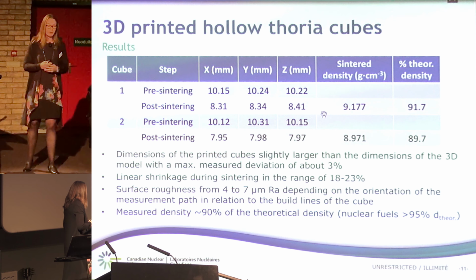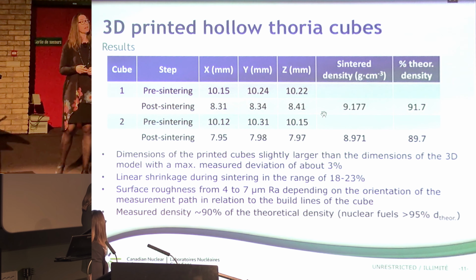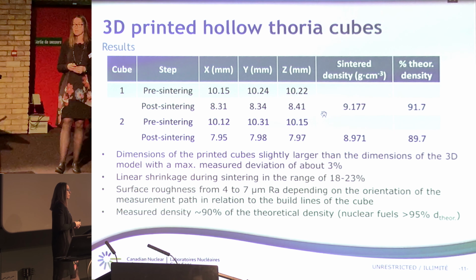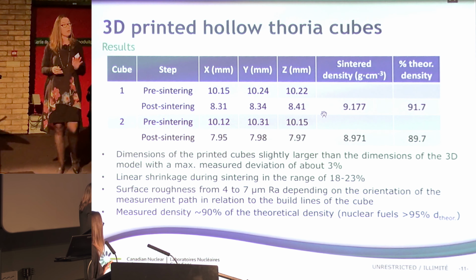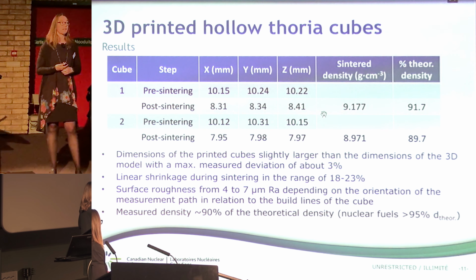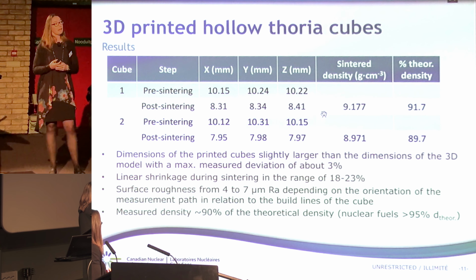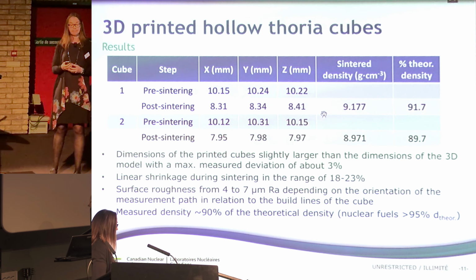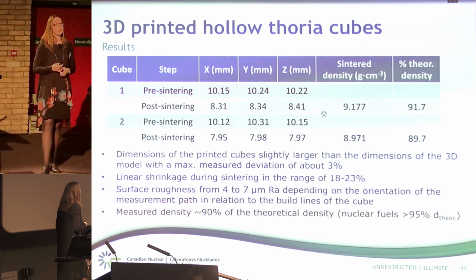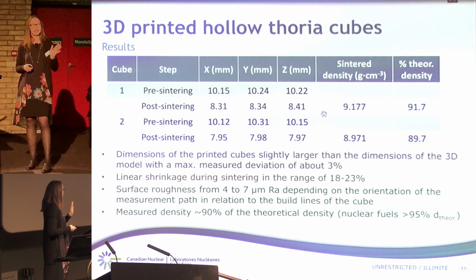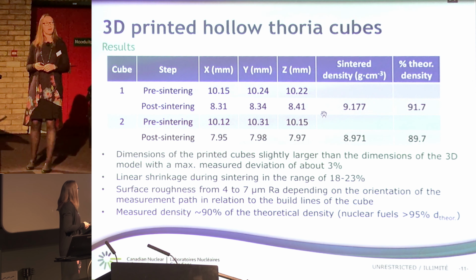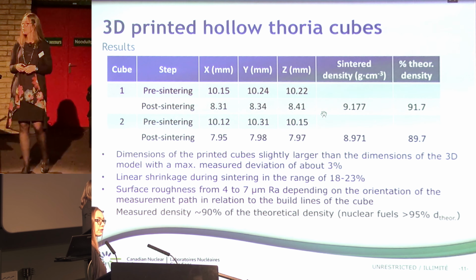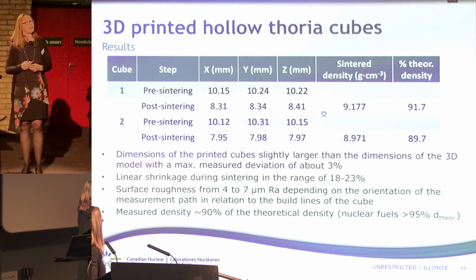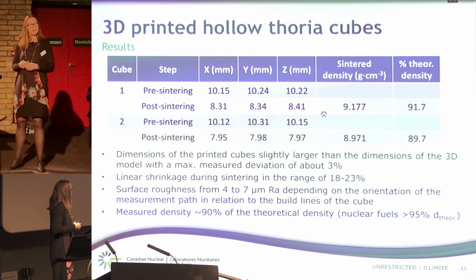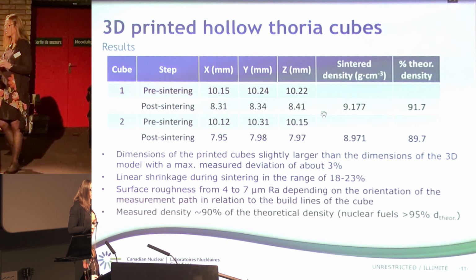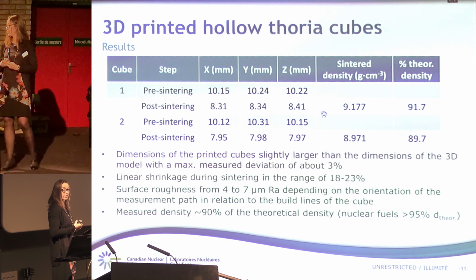You may have seen in the photograph shown in the previous slides that the surface finish of the final parts is a bit rough, which is about 10 times higher than the accepted surface finish for CANDU fuel. But my understanding is that those measurements will be acceptable for a light water reactor surface finish. Anyway, the surface finish also depends on the orientation of the measuring path in relation to the build line of the cube.